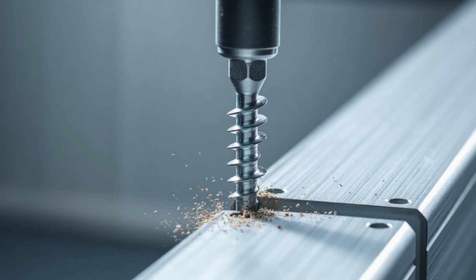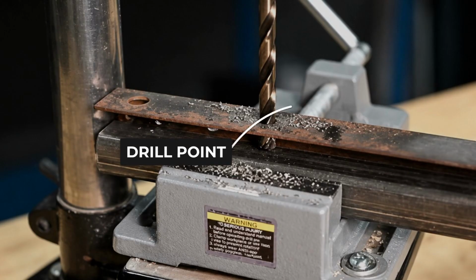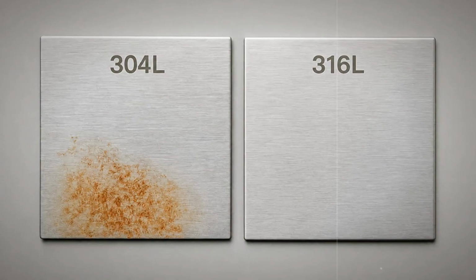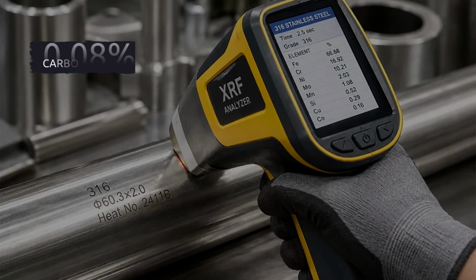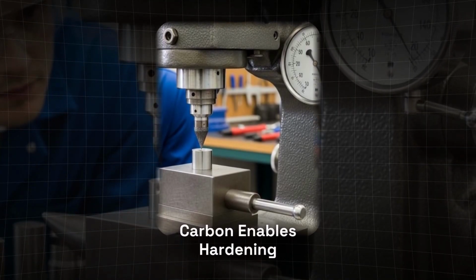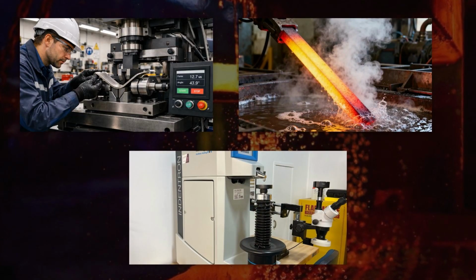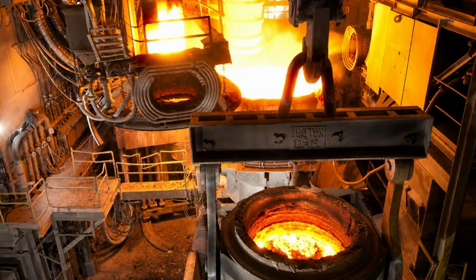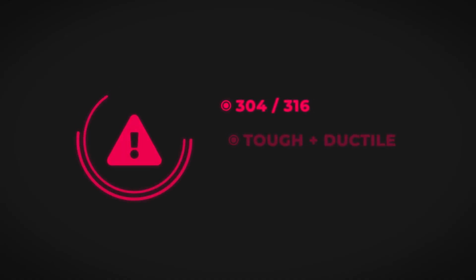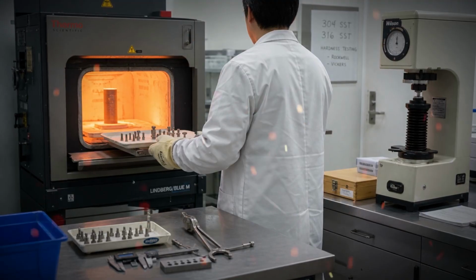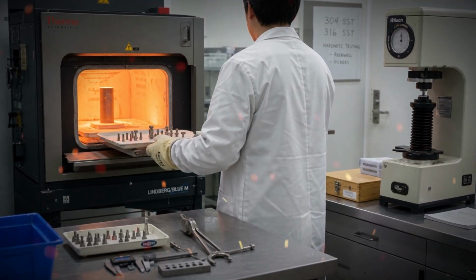That convenience carries a physical requirement. The point of the screw has to be harder than the steel it is cutting. Austenitic stainless cannot deliver that, and the reason sits in the same number that makes it corrosion resistant. Carbon content in 300 series stainless runs below 0.08%. Carbon is what allows steel to be hardened. Heat it, quench it, and the carbon locks the crystal structure into something brittle and hard. Strip the carbon out, and that mechanism disappears. The alloy stays tough, stays ductile, and stays soft no matter what you do to it in a furnace.